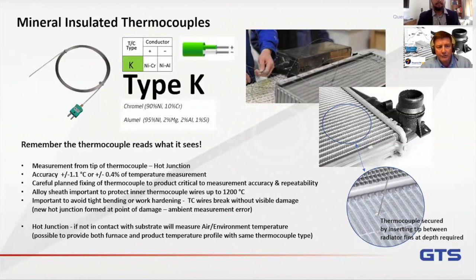Typically, the hot junction is at the tip of the thermocouple, but if you break it or snap it, a new hot junction will form somewhere along the length of the cable, which is not where you want that measurement to be. So be careful of the thermocouple, and also be very careful how you place your thermocouples. Spend some time designing an experiment to know how to physically secure the thermocouple tip in the radiator itself, sandwiched between the fins where you want it to measure.